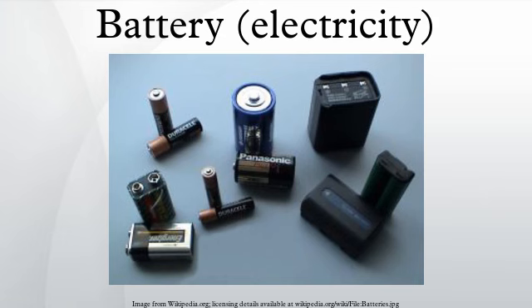Old rechargeable batteries self-discharge more rapidly than disposable alkaline batteries, especially nickel-based batteries. A freshly charged nickel-cadmium battery loses 10% of its charge in the first 24 hours, and thereafter discharges at a rate of about 10% a month. However, newer low self-discharge nickel metal hydride batteries and modern lithium designs display a lower self-discharge rate.